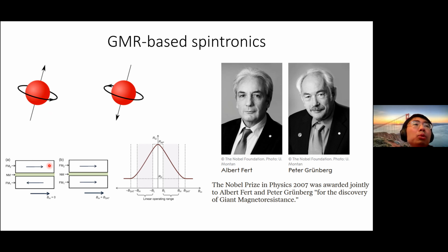The idea is the following. Imagine you have two regions. These two regions have different polarization of the spin. If the polarizations of the spin are opposite in this case, then if you measure the current going between the two regions, because there's a mismatch between the spins, the current is small. On the other hand, if the two regions have the same spin polarization, you have a larger current. So by switching the spin of the system, you can also change significantly the resistance in such a system. This is known as giant magnetoresistance.